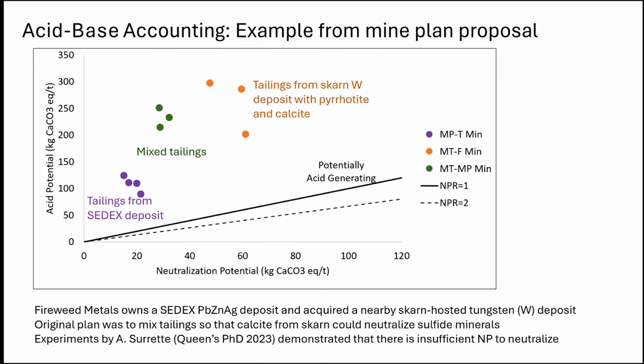And so a former PhD student of mine, Ali Surratt, created these tailings by doing flotation in the labs in the mining department here, and tried mixing them. And then she measured the acid potential and the neutralization potential to see what happened. So here are the tailings from the SEDEX deposit, and they're above this line, which represents an NPR of 1, or neutralization potential ratio. So they're potentially acid generating. Everything above that line is a PAG material. So we weren't surprised that these would be.